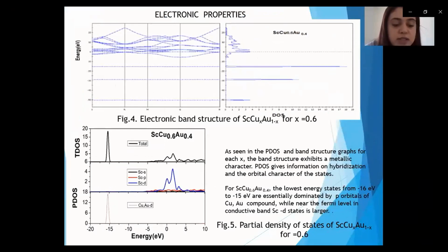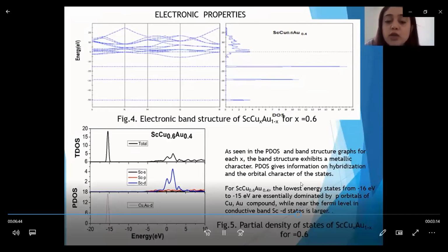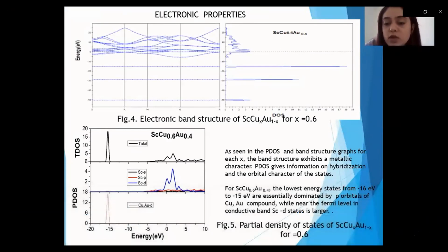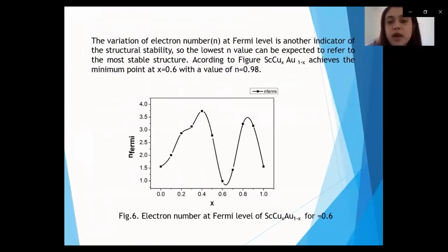The formation energy for the most stable structure is given in Figure 4. Figure 5 shows us the partial density of states of scandium copper gold X for X equals 0.6. For scandium copper 0.6 gold, the lowest energy states from minus 16 eV to minus 15 eV are essentially dominated by p orbitals of the copper gold compound, while near the Fermi level in the conduction bands, scandium d states are larger. The variation of electron number at the Fermi level is another indicator of the structural stability, so the lowest N value can be expected to refer to the most stable structure. According to the figures, scandium copper gold achieves the minimum point at X equals 0.6 with a value of N equals 0.98.